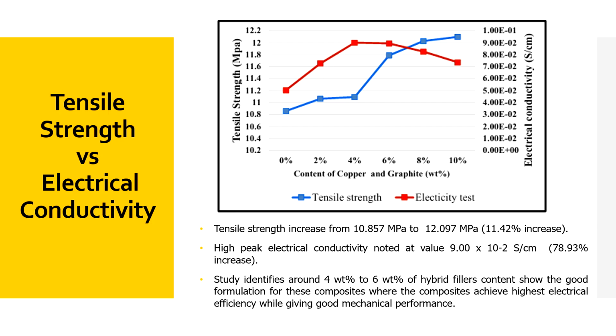So if we compare the results for tensile strength and electrical conductivity, we can find that with the addition of hybrid conductive fillers, there was an increase in tensile strength and electrical conductivity with the increase of the hybrid filler content.